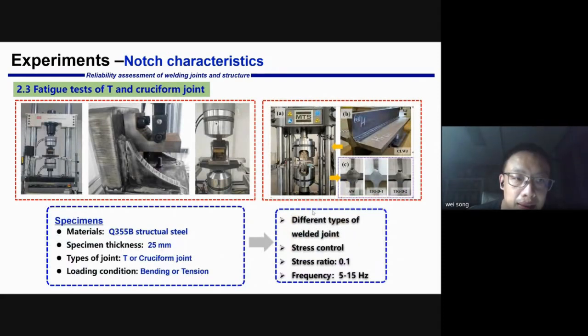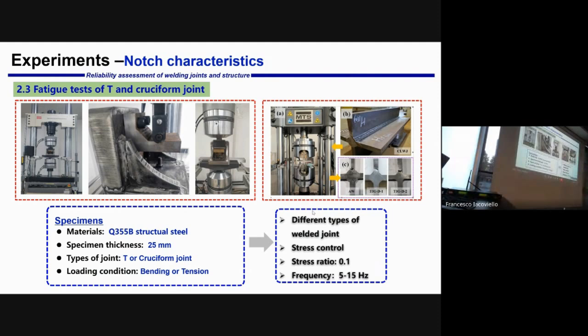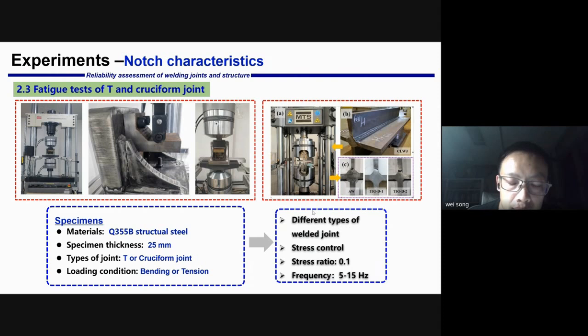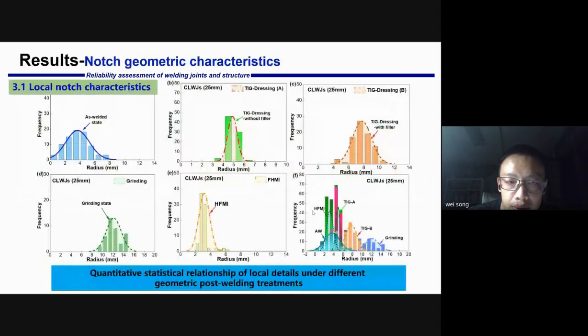For the test of the single T and the cruciform joint, we use the Q355 structural steel, and the specimen thickness is about 25 millimeters under bending or tension cyclic loadings. Before the fatigue test, we first get the local notch characteristics by blue scanning technology. So we can get statistical results for different geometry parameters.